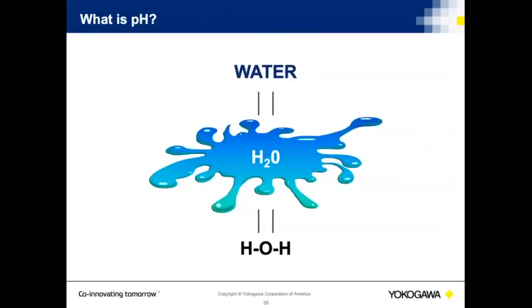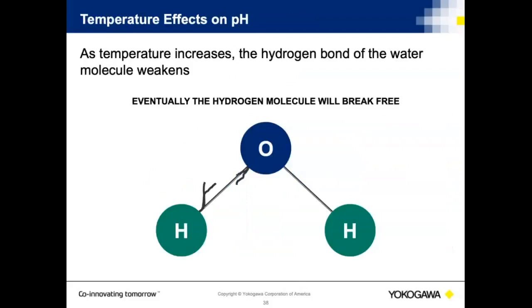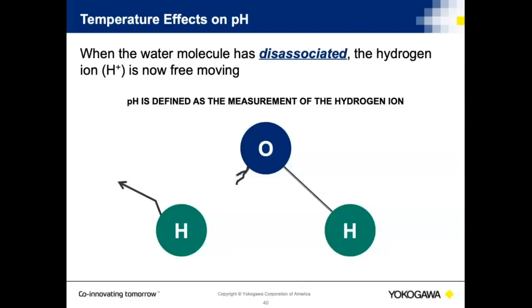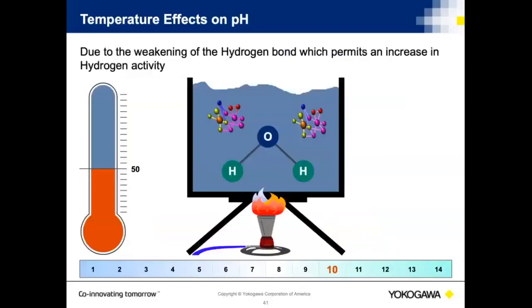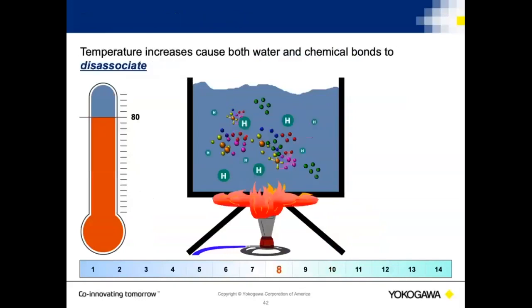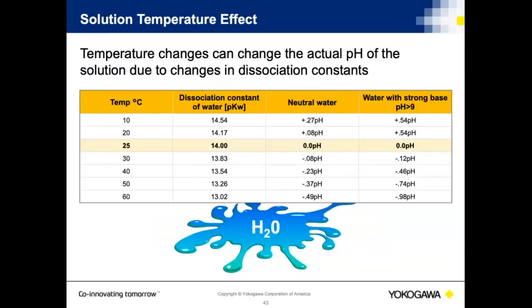Water, we know when we look at water, as the temperature increases, the hydrogen bonds will break down more frequently. As they disassociate, the hydrogen molecule is now free moving, and I'm measuring the hydrogen ion concentration on that glass electrode. This just illustrates it briefly. If I'm at 10 pH and I start to heat that vessel up, more hydrogen ions disassociate. It's that disassociation that I'm going to compensate for.